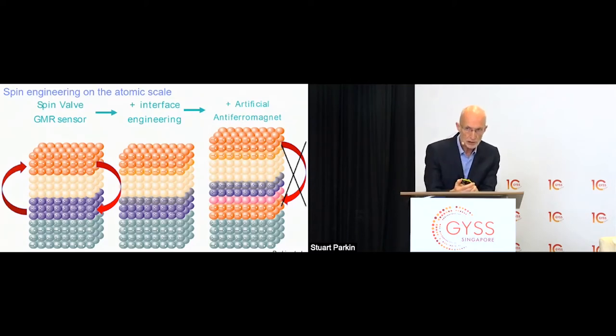However, on useful dimensions for a recording head, the device has to be on the nanometer scale, 10, 20 nanometers in size. And this means that the magnetic layers, shown as red and blue, the magnetic poles at the edges of the device give rise to dipole fields. And these dipole fields on nanometer scale are very strong. And that's why I've drawn this device showing the red and blue layers antiparallel. The dipole fields will automatically align the two magnetic layers antiparallel because of the strength of this dipole field. So we have to find a way to eliminate these dipole fields to make useful devices that can respond to tiny magnetic fields. And again, this is a proposal I made.